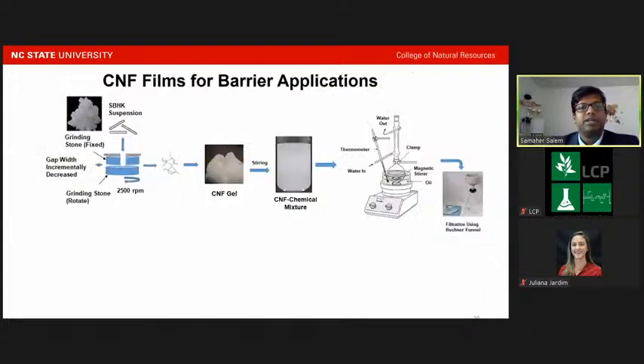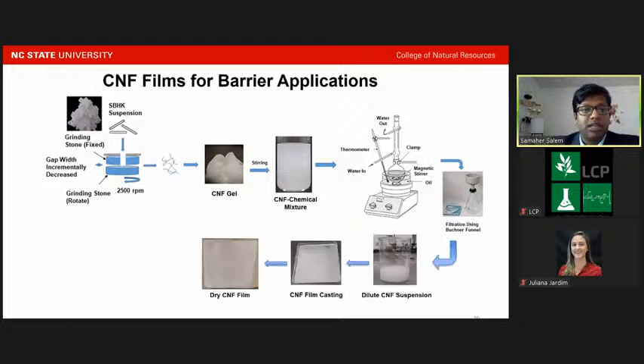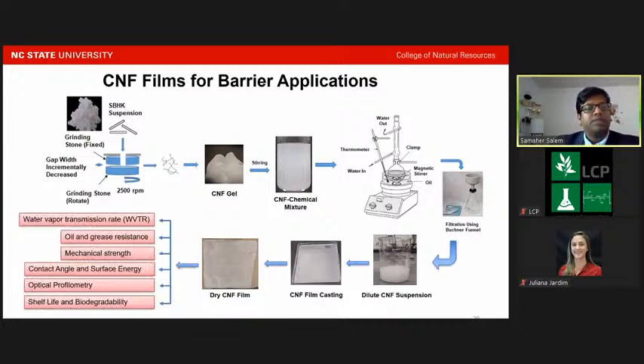Further, we evaluated the barrier applications for these films and how this reactivity affects the barrier properties of the nanocellulose films. We acetylated and modified the nanocellulose in the same way, and then we diluted the modified suspension and, using the film casting method, produced the dry film. Then we measured the water vapor transmission rate, oil and grease resistance, mechanical strength, contact angle, and surface energy. We also did optical profilometry, shelf life, and biodegradability.